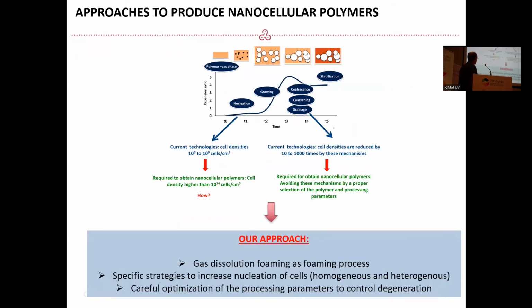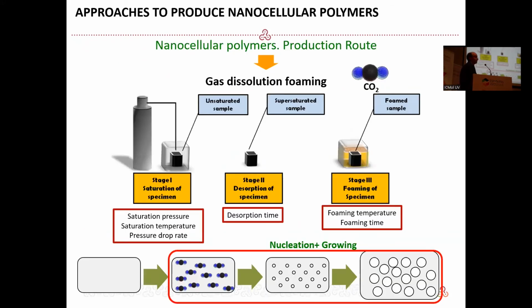And in order to do this, we have used gas dissolution foaming. I will explain very briefly. In gas dissolution foaming, we have a polymer. In this polymer, we introduce CO2 by just increasing pressure. So we put the polymer into a pressure vessel, we introduce CO2, and the CO2 is dissolved into the polymer. Then we release the pressure, and we have the CO2 inside the material. But as we have lower pressure now, the CO2 is oversaturated. So just by heating, we create the cellular structure. The cells nucleate, the cells grow, and if we control the process carefully, the cells stabilize.